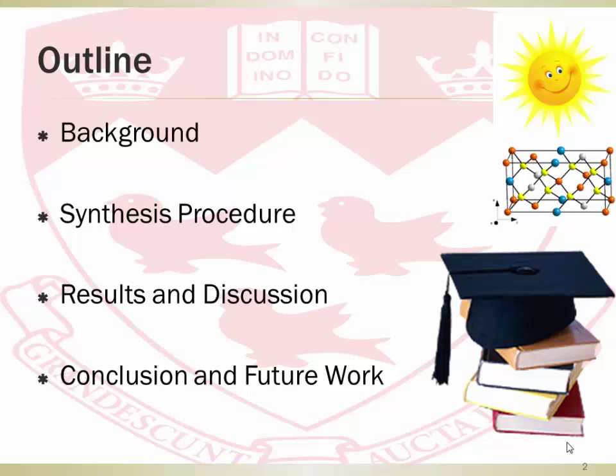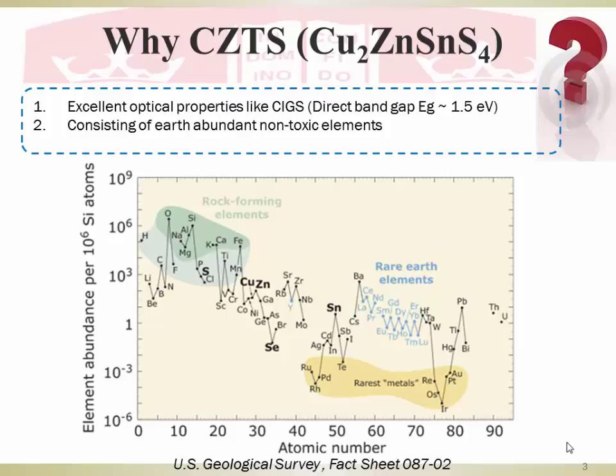First, I would like to give a brief introduction about CZTS and why it has attracted attention in the photovoltaic field. The main reason is that CIGS — copper indium gallium selenide — is a material widely investigated in thin-film photovoltaics with efficiency beyond 20%. CZTS is like the little brother of CIGS with similar optical properties. Unlike CIGS, CZTS contains only earth-abundant, non-toxic elements, making it more attractive in terms of environmental and cost considerations for solar cells.